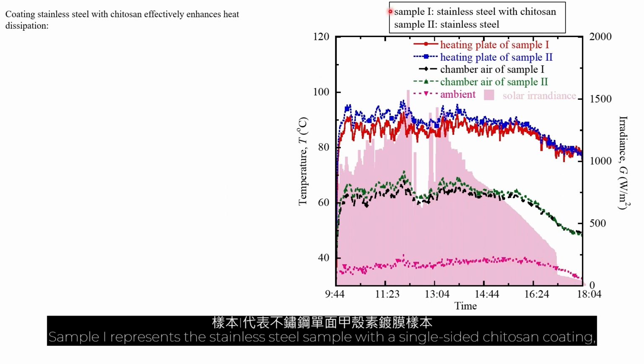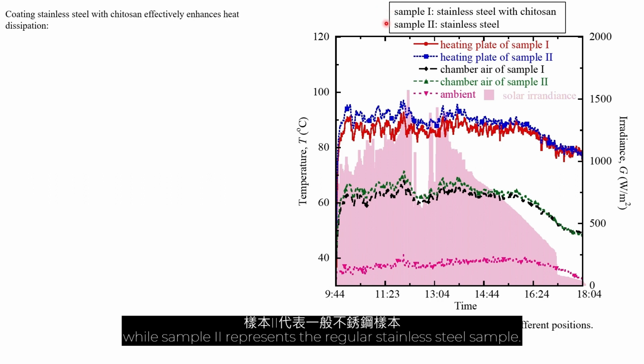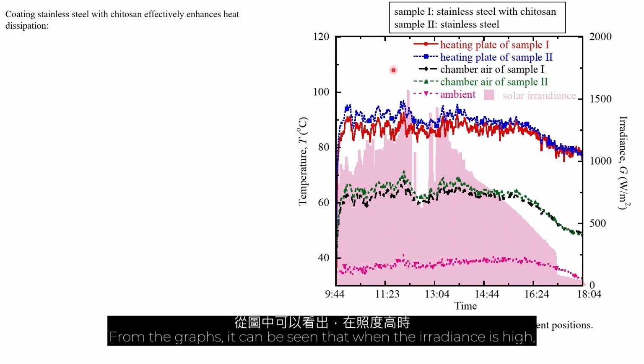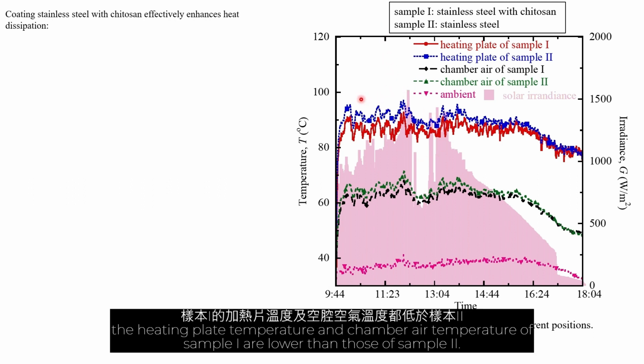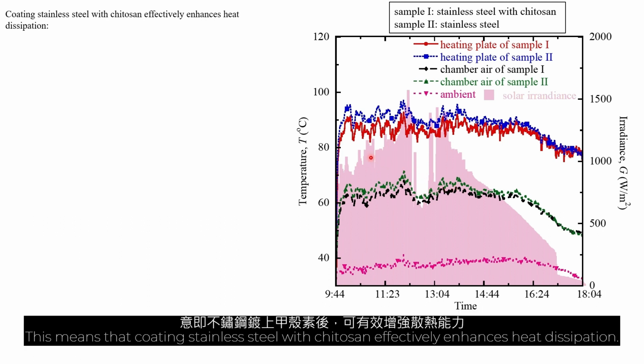Sample 1 represents the stainless steel sample with a single-sided chitosan coating, while sample 2 represents the regular stainless steel sample. From the graphs, it can be seen that when the irradiance is high, the heating plate temperature and chamber air temperature of sample 1 are lower than those of sample 2. This means that coating stainless steel with chitosan effectively enhances heat dissipation.